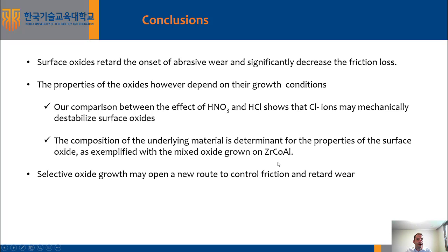So with this, I would like to conclude that surface oxides retard the onset of abrasive wear and significantly decrease the friction loss. The properties of the oxides are, however, dependent on their growth conditions. So if we now compare the effect of nitric and hydrochloric acid, we find that chlorine ions may mechanically destabilize the surface oxide, which results in the smearing of the oxide layer upon sliding.